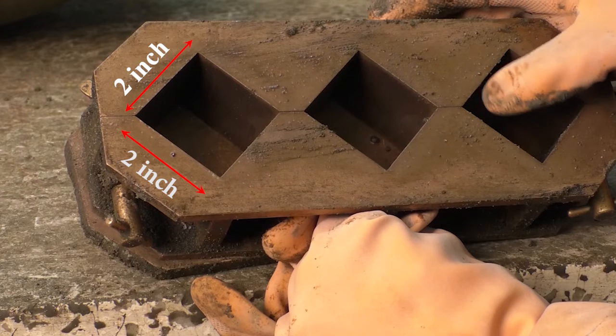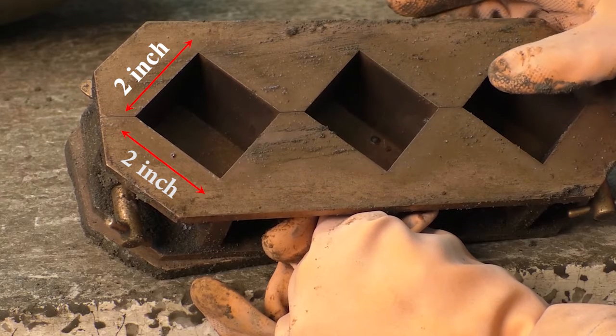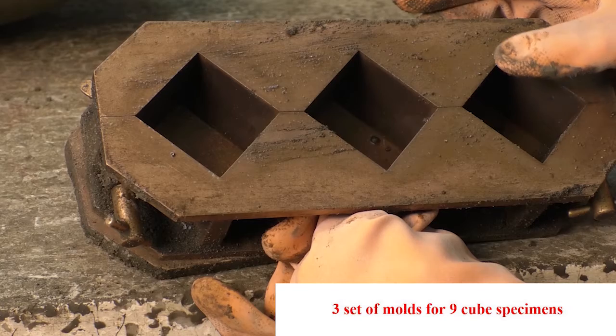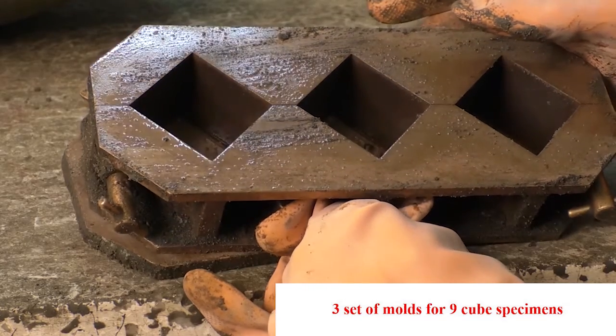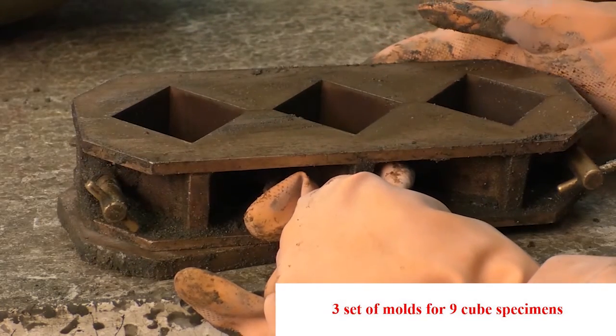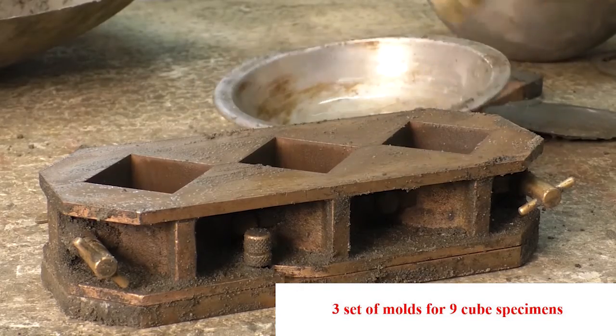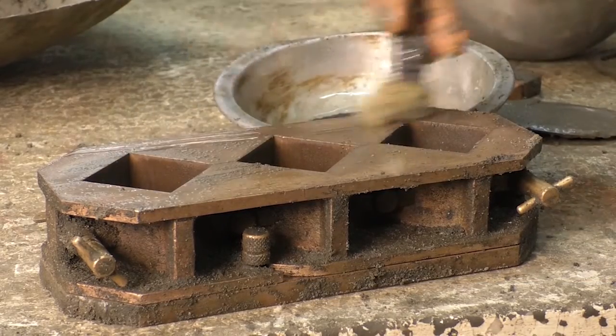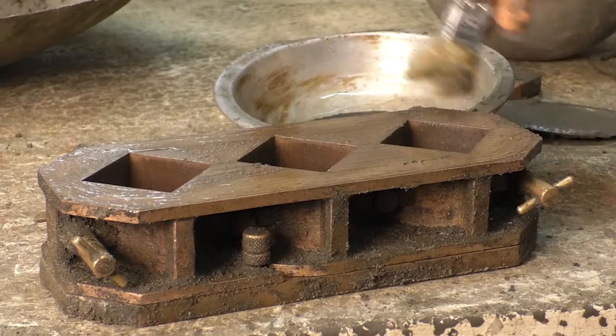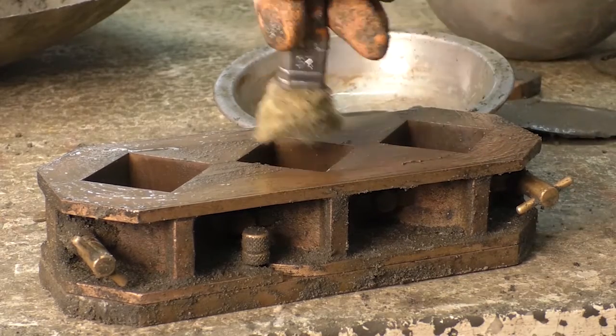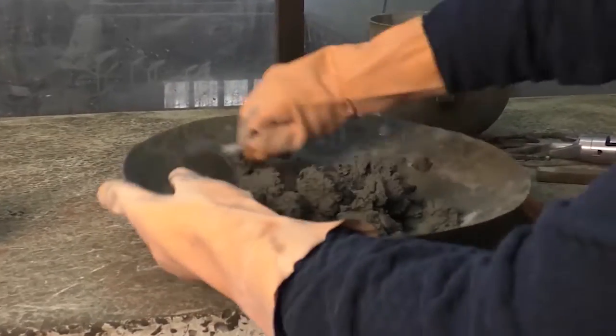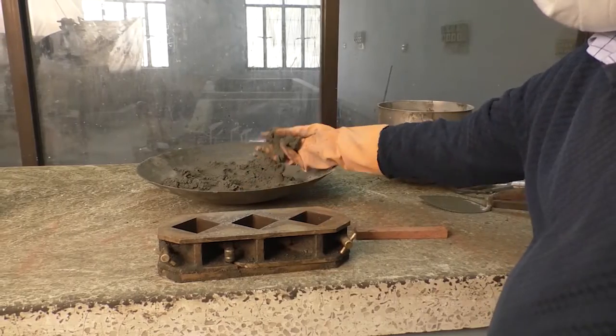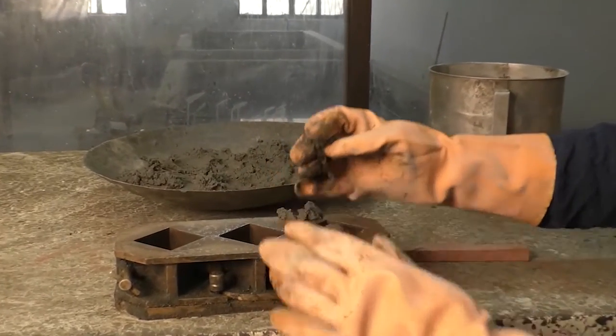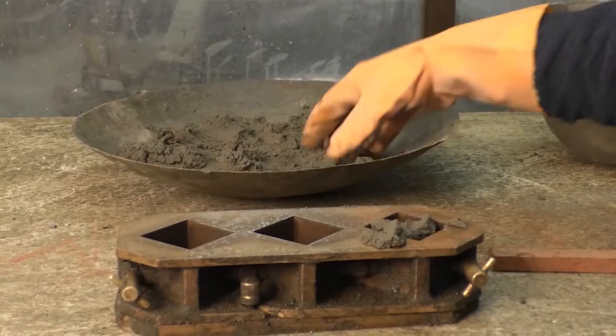This is the mold used for preparing 2-inch cubes. We will be using 3 molds for preparing the 9 cubes required for our experiment. We have to brush oil onto the surface of the mold so that the cubes can be easily removed from the mold. We have to start molding the specimens within 2.5 minutes after completion of the original mixing of the mortar batch.